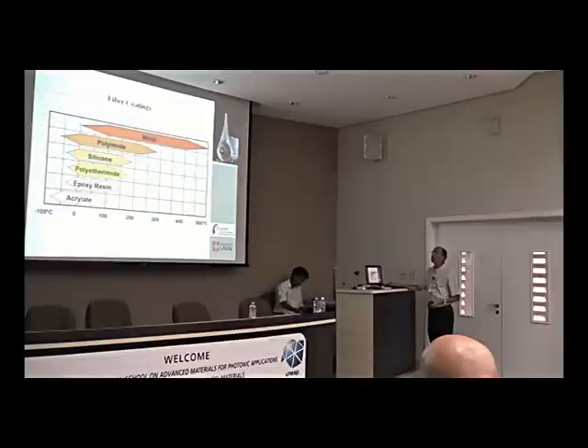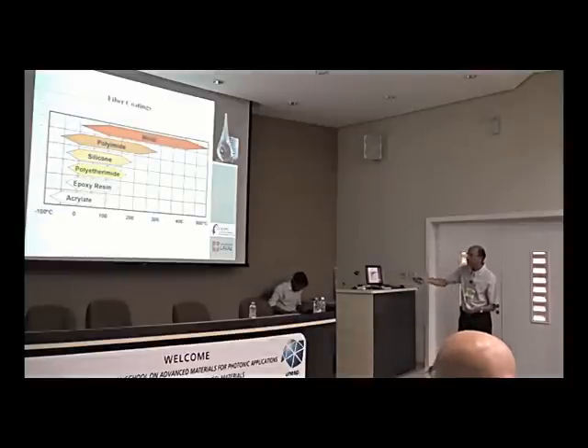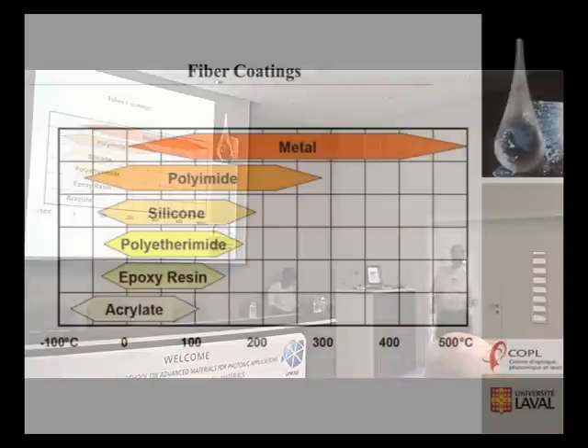As I said, sometimes not only the core and cladding are so important, but the coating at the surface is also important, because of the property that we are looking for. I give this transparency to show you the different coatings that we have been able to have, and also the range of temperature stability of such coatings. The first one is acrylate, which is stable between -50 to 100 degrees C. Epoxy till 150, polyetherimide till 180, silicone, which we use a lot, between -20 till 190, and polyimide, which has a lot of applications, stable till 280, and finally metal layers or metal coating. This is so important because it covers a large range of temperature till 500 degrees C.